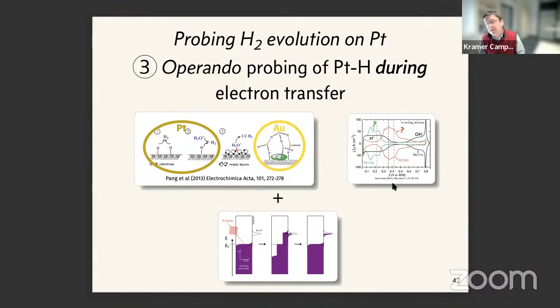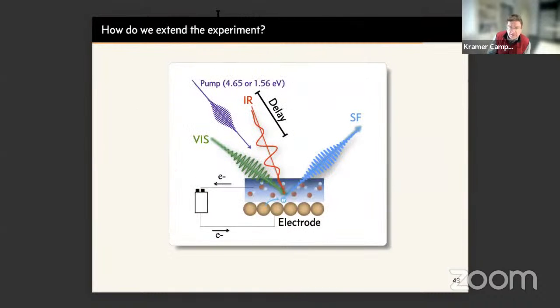And in the last few minutes, what I want to do is put these together into one experiment. So I want to excite with this same femtosecond optical pulse and probe the platinum hydrogen spectral response. So this thing is shown here. What we do now is combine this sum frequency, in this case with a 1.56 eV pump pulse.